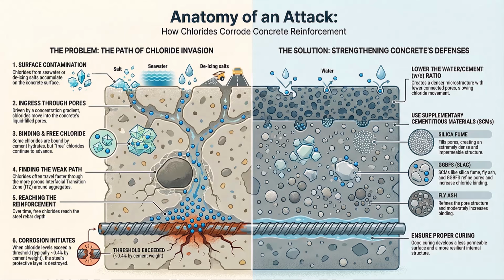The most critical parameter is the water-to-binder ratio, or W/B. The required minimum is less than or equal to 0.40, but the recommended value for maximum safety and durability in a severe environment is less than or equal to 0.38. This forces an extremely dense, impermeable paste. And the SCMs have to dominate that mix.